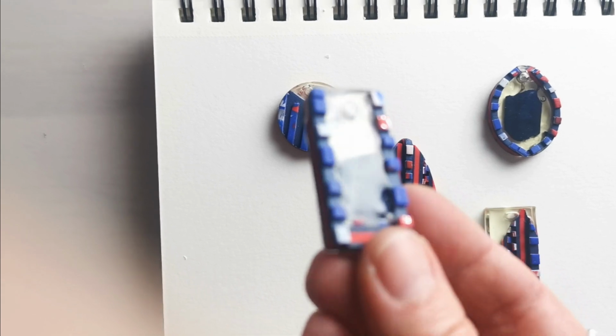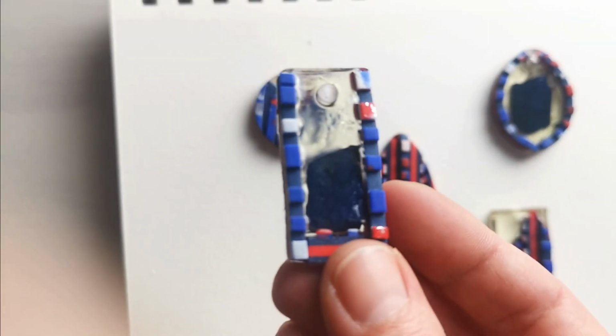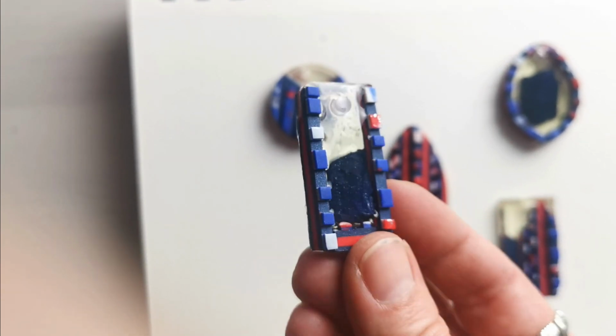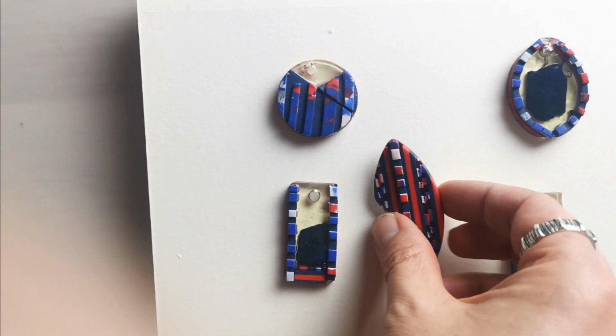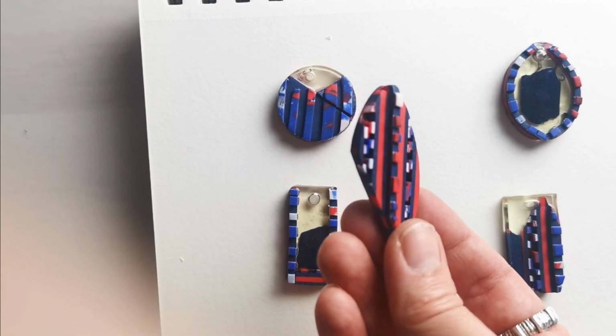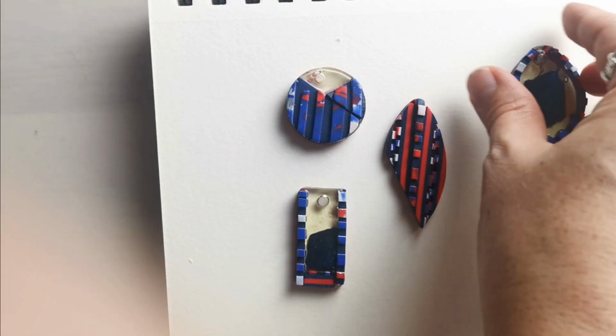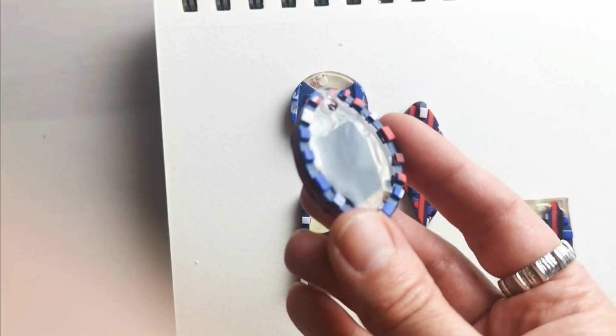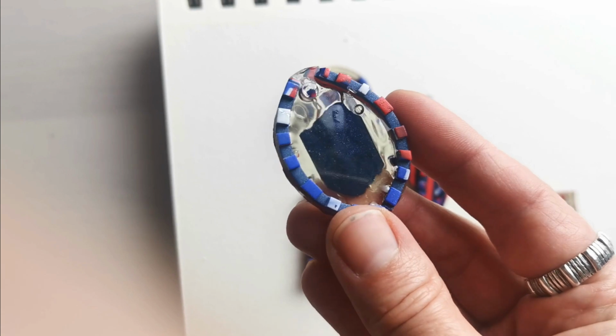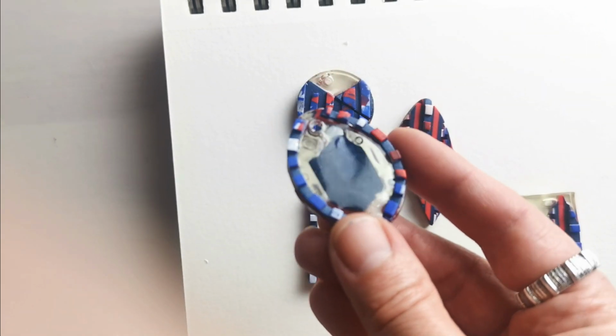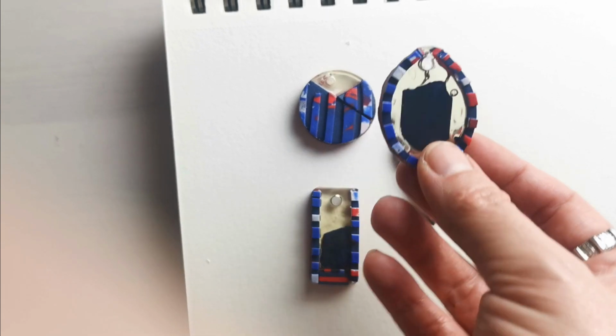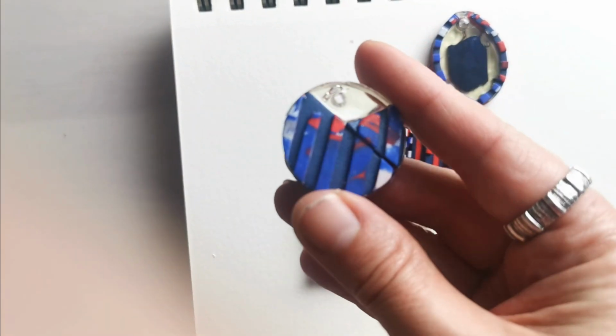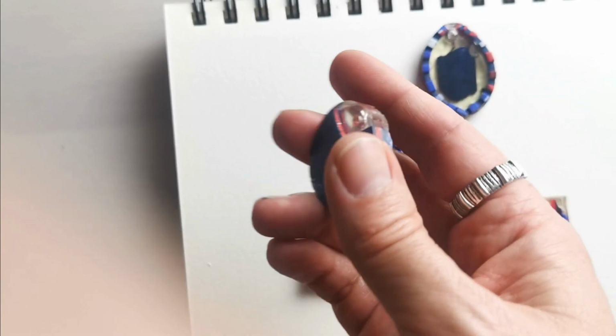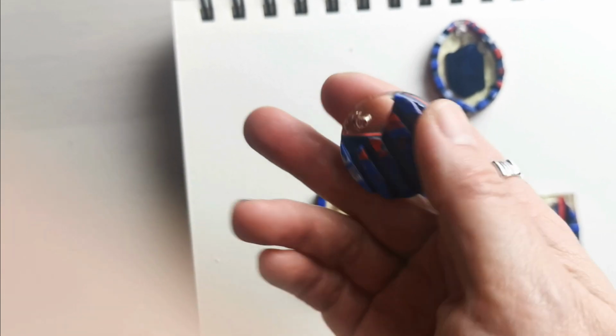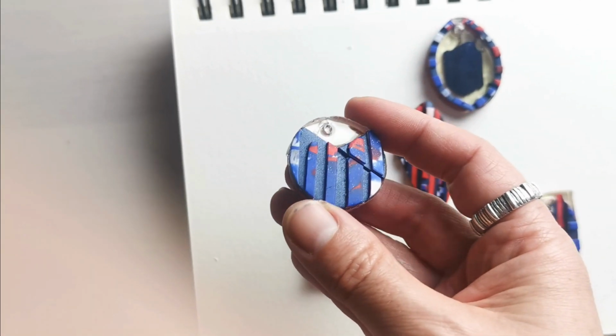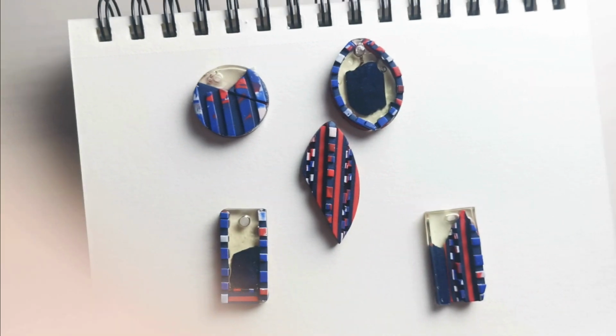And I have to tell you that when I used the black mold, I could not see properly if there were bubbles inside the resin. So I had more resin bubbles inside those molds, which again, it's better to use a light color or transparent mold, because you have better visibility and you will be able to take out any air bubbles. And you can also use a heat gun from a distance and remove such air bubbles.